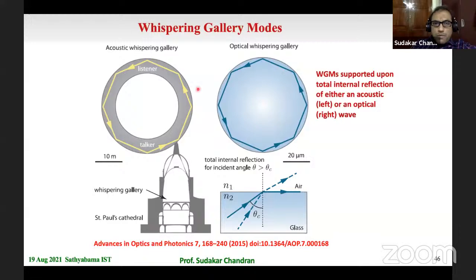The optical version of this is the optical whispering gallery. Of course, sound waves are larger, so you need structures of several tens of meters, whereas for light waves, the wavelength is very, very small. It's anywhere from 400 to 700 nanometers, so for visible light you need micron sized structures, and the spheres serve the purpose. So when the light gets total internally reflected inside the sphere, it gets trapped and circulates around, establishes a resonance, and therefore you get very intense scattering.